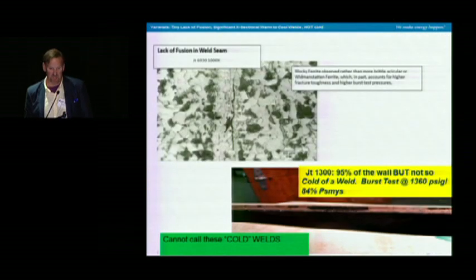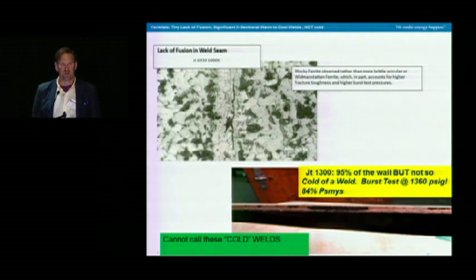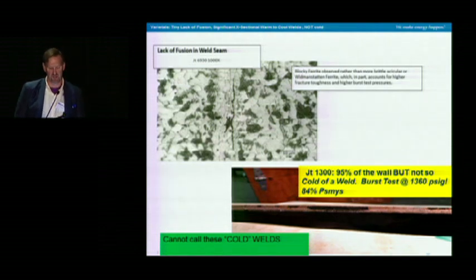So, pictures. Jim likes pictures, I like pictures. Yes, if we look close enough, will we find some lack of fusion out there on this pre-60 ERW? Yeah, and if you look at the scale, 10 microns, I am not going to go worrying about a 20 micron length, quote unquote, lack of fusion. A lot of the testing we've done, a lot of the metallurgical sections that people brought up that we need to do, there's no arguing that.